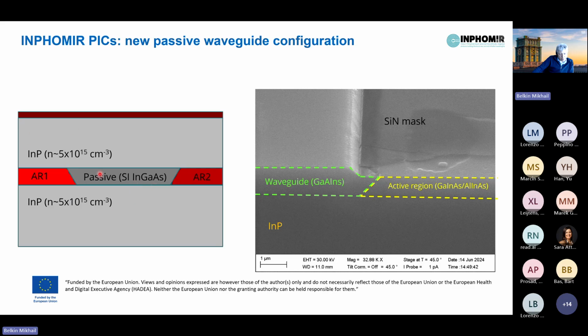And then we use the common upper cladding layer for the entire structure. We use very low doping for the cladding layer because high free carrier concentration would strongly affect the losses at mid-infrared frequencies. But at 5 times 10 to the 15, we introduce no more than 1 dB per centimeter additional loss, actually significantly less than 1 dB per centimeter additional loss, even at 8 micron wavelengths in that passive waveguide.